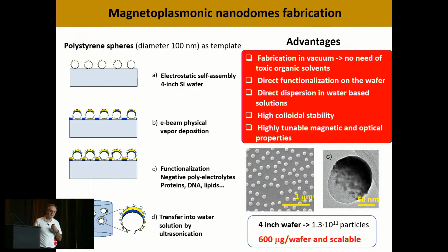And this approach has several advantages. First, we fabricate in vacuum, meaning that we don't need any toxic solvents to make our nanoparticles, in contrast to iron oxide, for example, where you use chemical synthesis. We can functionalize directly on the wafer, this step here. And it's very easy to disperse the nanoparticles in water. We don't need any surfactant, just ultrasound. And as I will show you later, using this approach, we can tune both the magnetic and optical properties of the nanoparticles.